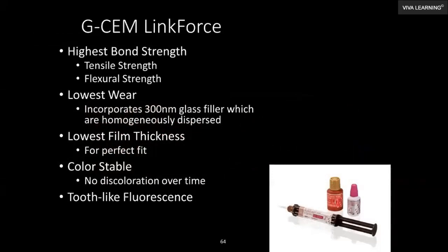Why do I use Link Force? Because it comes in a variety of shades. It has very strong bond strength. There's very low wear if I should have any at the margin, which I'm not going to have. The film thickness is low, yet when I place the veneer on the preparation, in this case, it won't slump or slide. It'll actually sit exactly where I place it. And that's the funny part of some of these cements, in that the runny ones, if you place a veneer on, it's going to slide or move right off.